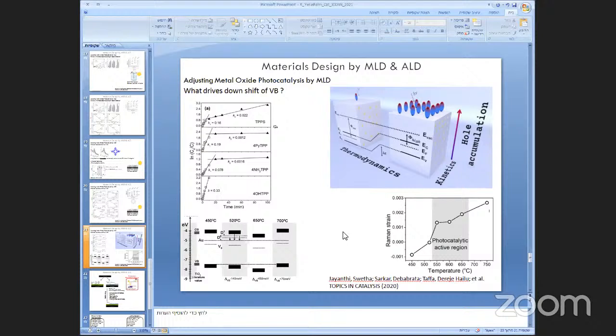Okay, very good question. All the studies that I showed you here were done where these hybrid organic-inorganic films were annealed under air or oxygen. The reason we do it is we have carbon in the system, and we don't want to necessarily get carbon-doped titania. If you anneal it under hydrogen, you may get a totally different material starting from this organic-inorganic hybrid, and this is indeed a very important parameter.